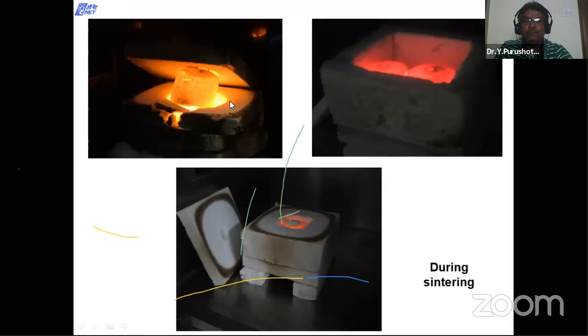If you see this during the sintering, we took some pictures. You can see the entire ceramic casket is not heating, but only the susceptors are heating, selective heating. If you put it in a conventional furnace, everything will be in a hot condition, whereas here only the sample is in hot condition. So, selective heating.